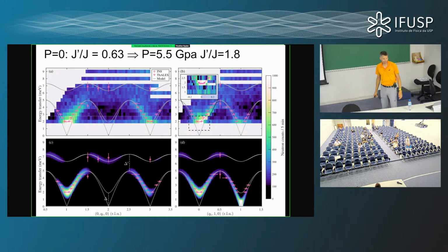Okay, thanks. So, can you extrapolate and find the sweet spot to find all phases between 0 and 5.5 gigapascal? Because in principle, you have both values of J prime. So in principle, you could at least guess the pressure, to guess the plaquette phase and the other phases in this compound in between those two phases. Sorry, I couldn't... No, I'm sorry. So in principle, I'm just asking if you could guess the pressure, because you have the values of J prime for zero pressure and 5.5, right? So can you guess the value of pressure you'd need to go to, let's say, precisely inside the plaquette phase? We have a quite good idea.